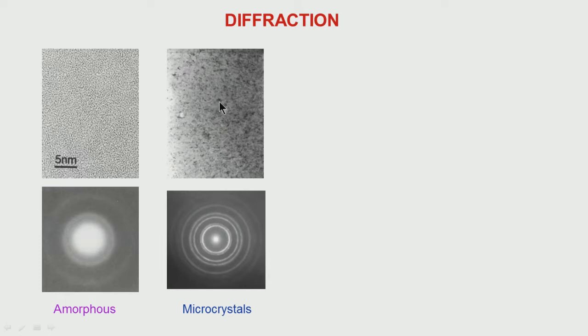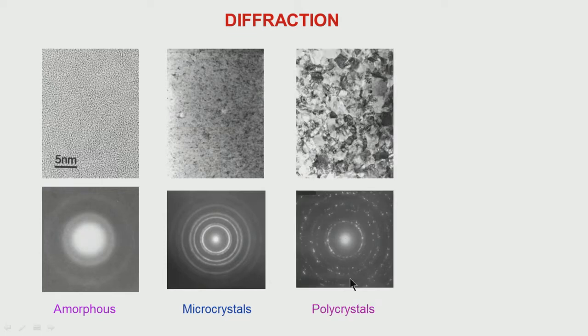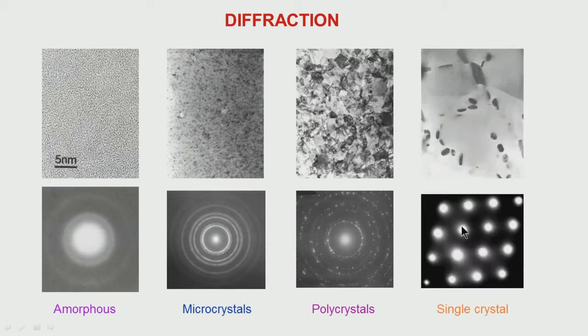If you look at that image, from region to region, we can see that some regions are bright, some regions are dark. This is because of how the crystals are oriented with respect to the incident beam. In polycrystalline materials, a semblance of a ring is there, but we see spots in some rings, not continuous. Here also we can see the contrast. When the grain becomes very large, we get a single crystal diffraction pattern, and we can see the different grains and the second phase particles. Here all the contrast which is coming is because of diffraction effects.